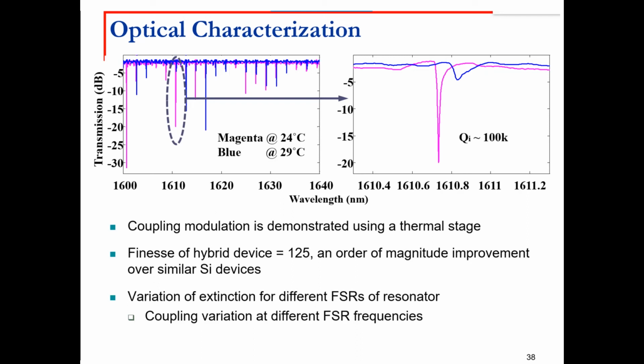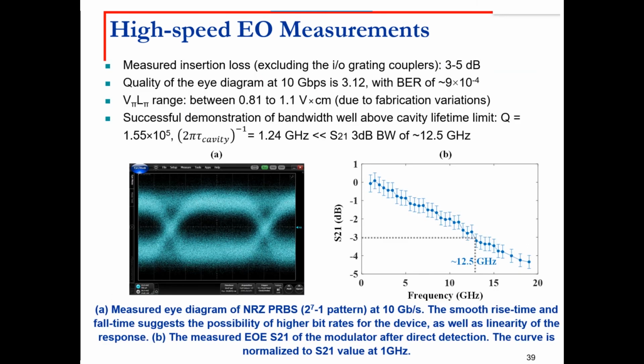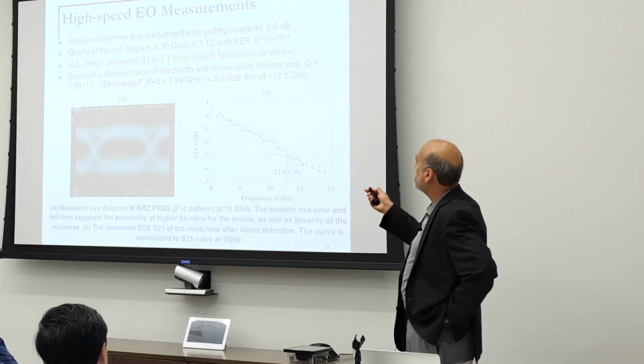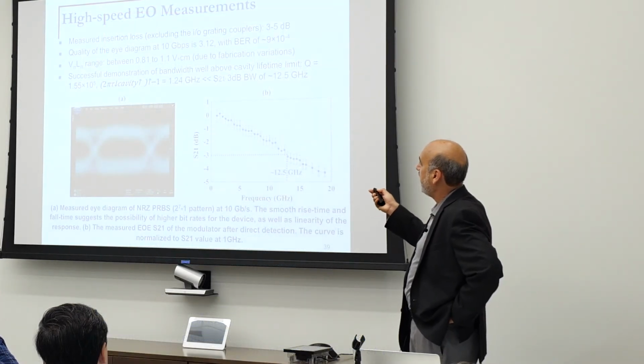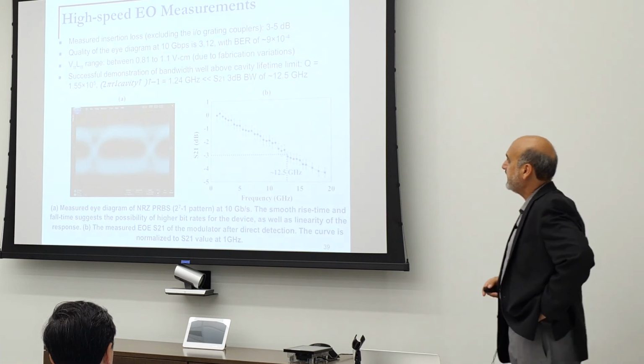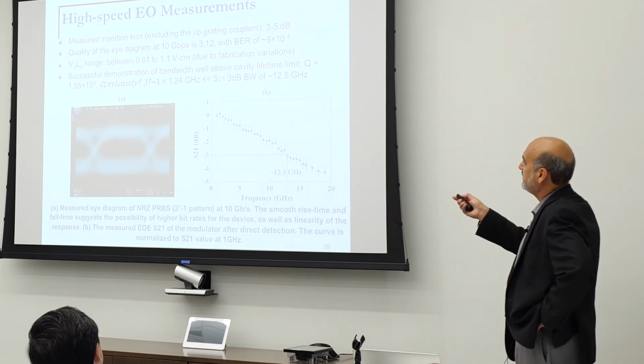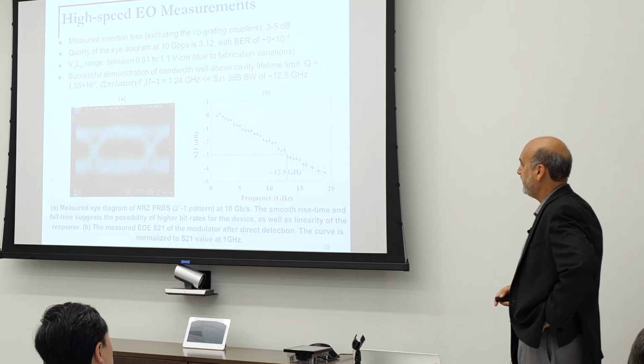And this is the actual transfer characteristic and the eye diagram of the device. Just to mention a few things. Number one, this is a high Q resonator. The lifetime of the cavity tells us that, if it was conventional, it would work at 1 gigahertz, nothing more than that. This easily works at 12 gigahertz without a problem. A bit error rate of 9 times 10 to the minus 4 is achieved at 10 gigabit per second. And the insertion loss is only 3 to 5 dB.